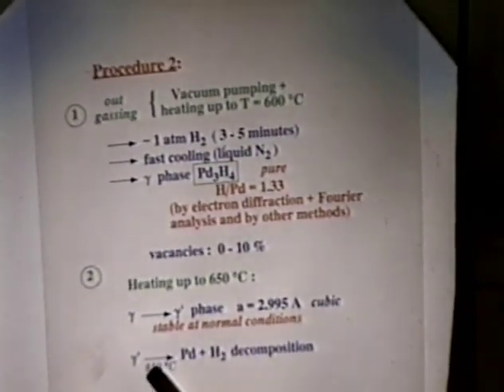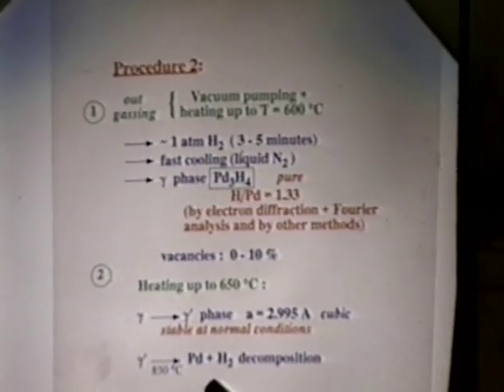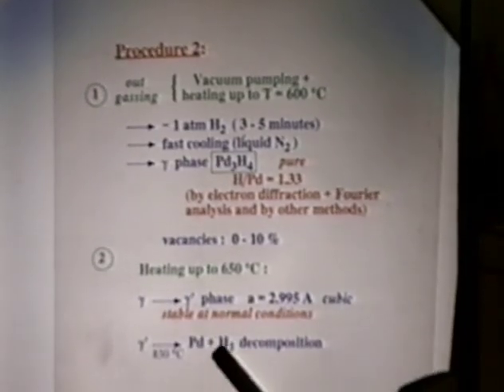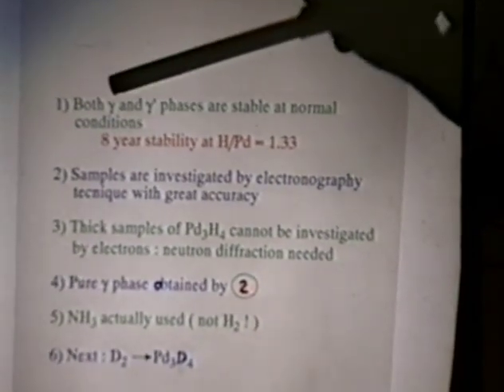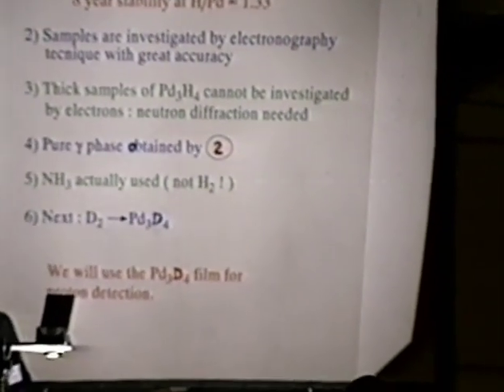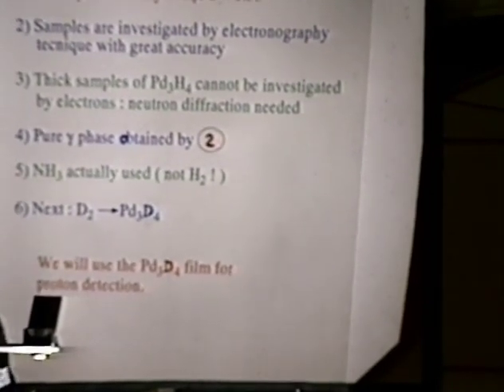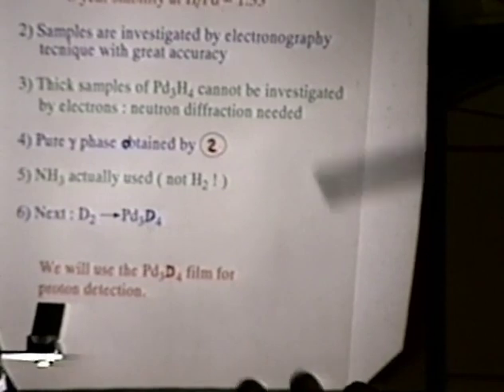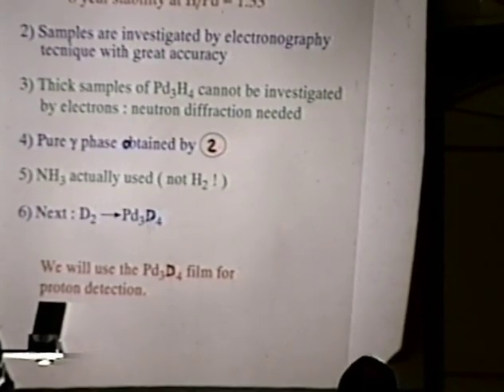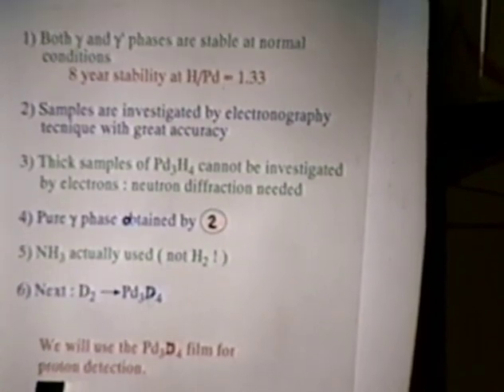If you heat up not at 650 degrees, but 850 degrees, then you get the decomposition of palladium and hydrogen in a separate phase. So we have both gamma and gamma prime phases stable at normal conditions, even 8 years stability with this incredible ratio. The samples have been carefully investigated by electron diffraction.